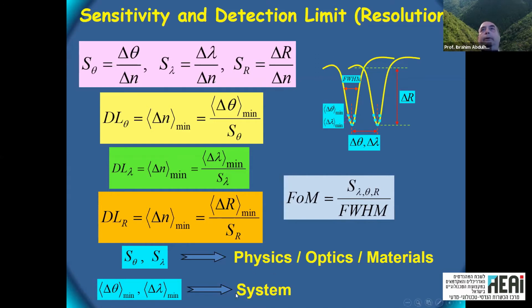And you can easily think about it because if the full width half maximum is very large, it will be like a very wide spectrum. And if it's slightly noisy, then you will have large error in determining the minimum of the resonance. Okay, so it depends also on your system. That's why we define something called the detection limit, the resolution of the sensor, which will be the minimum value that we can measure. So the minimum shift will give us the minimum refractive index that we can measure, which means the minimum concentration of the analyte.